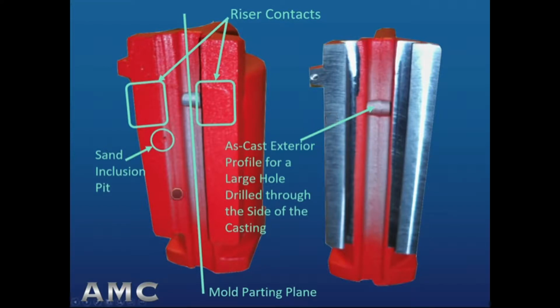Third, notice the sand inclusion pit. A judgment has to be made by the metal caster before the casting is shipped to the machine shop, whether or not that sand inclusion pit is deep enough to cause a non-cleanup in the mill surface.